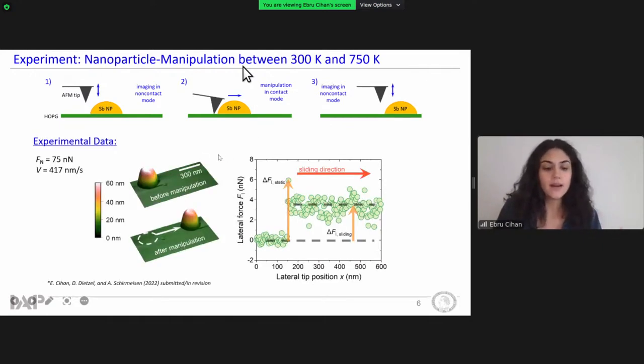So here is experimental data, where these are the AFM images showing the location of the nanoparticles before and after the manipulation, and here is the tip. And this shows the lateral friction signals during manipulation. The AFM tip gets in contact with the nanoparticle first at 150 nanometers, where we also see a sudden increase in the lateral force signal, which is the static friction peak. And then immediately after that, the particle begins to slide, which is the sliding friction.